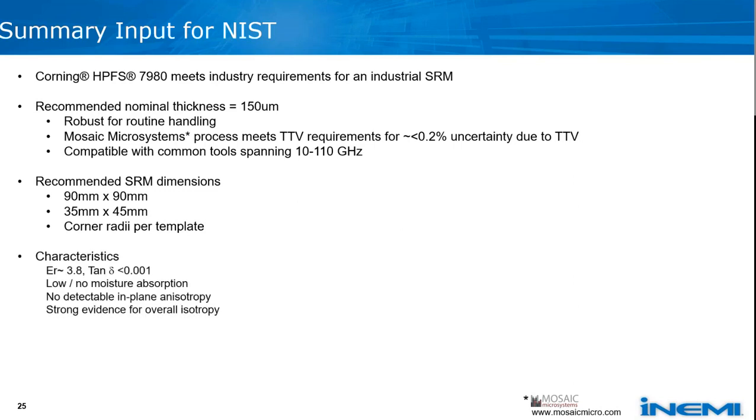From the user standpoint, the SRM ultimately ends up having a dielectric constant somewhere in the neighborhood of 3.8 with a loss tangent that's less than 0.001. So this represents a very good low loss material, again with low moisture absorption and high isotropy.